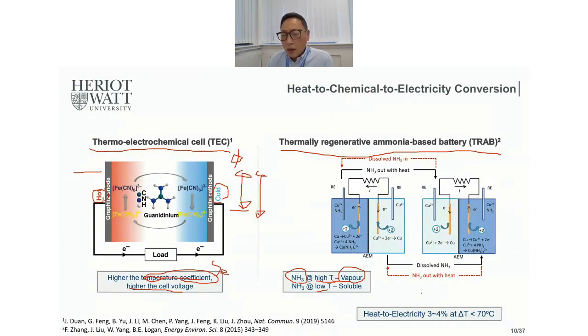battery. For those two cases, the heat to electricity conversion is already 3 to 4%. Of course, it is not a commercially proven efficiency, since these are lab scale studies. But at low temperature gradients, for example only 70 degrees C or less, they already show quite good efficiency, which is close to the maximum efficiency of semiconductor-based thermoelectric devices.